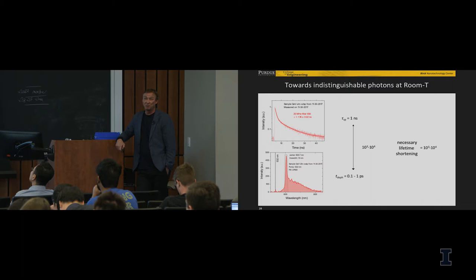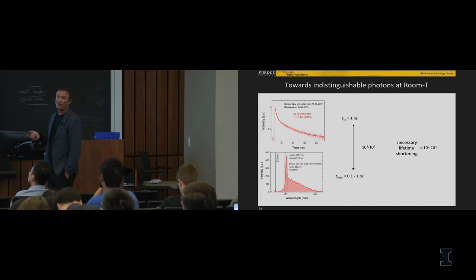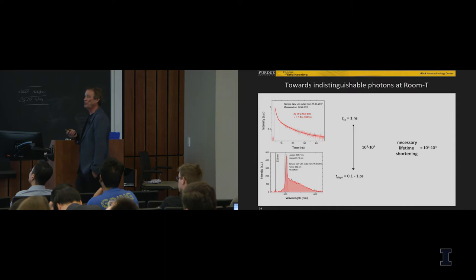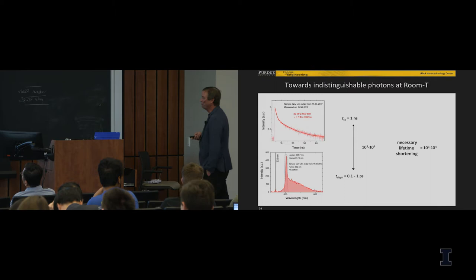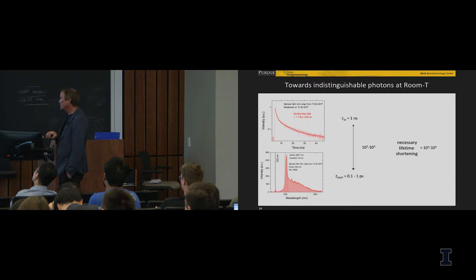Potentially, it could be, for example, germanium vacancy. In that case, the spontaneous emission lifetime is nanoseconds, and the dephasing time is between 0.1 and 1 picosecond. So you actually have to have this enhancement in light-matter coupling, this increase in spontaneous emission, of around 1,000 to 10,000. And for the previous system, we already demonstrated 3,500. We should be able to demonstrate it now, but we need to learn how to work with these good quantum emitters, and that's what we are doing right now. But at least clearly the concept works, and we should be able to do it.